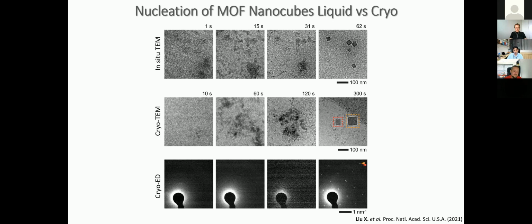So we take electron diffraction. Okay, homogeneous solution, amorphous. Phase separated, gold-rich, gold-dense solution, amorphous. These amorphous nanoparticles, amorphous. I mean, I already preemptively called it amorphous nanoparticles, but you see it's amorphous. And only when it collapses into a cube does the cryo-ED show that we have a crystalline phase, right?